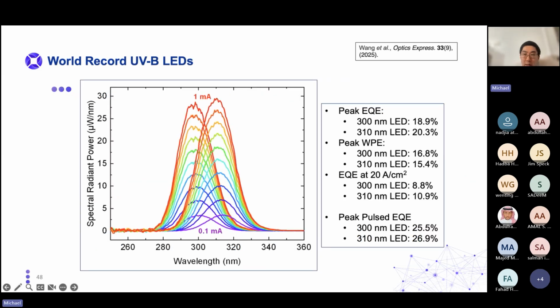So these are the numbers to summarize the results. With the 300 nanometer LED, the peak EQE is 18.9%. With 310 nanometer LED, it's 20%. Peak wall plug 300 nanometer LED is around 17%, and 310 nanometer LED is around 15%. These will improve significantly and be closer to the EQE with fabrication.